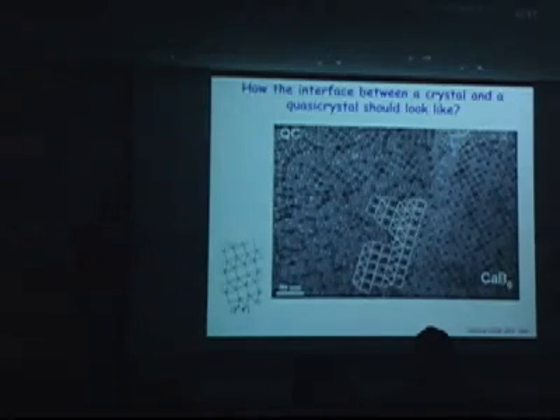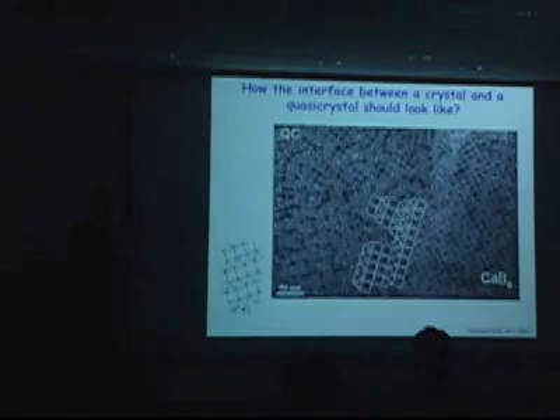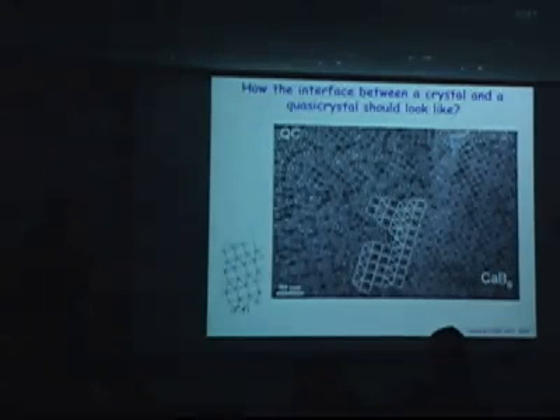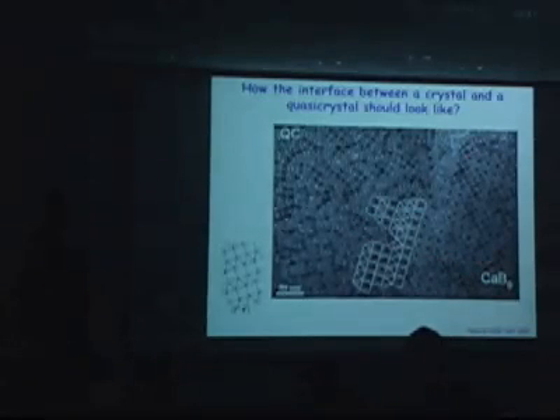For atomic systems, it was very difficult or nearly hopeless to study, because you need to map large areas with atomic resolution, and unambiguous atomic resolution. But with nanoparticles, it was a very simple experiment. We had many quasicrystalline domains, and all we had to do was look at what is at the edge of this domain, how it interfaces with the outside world. And we collected pretty large statistics of what's going on at the interfaces, and we found that indeed the dodecagonal quasicrystalline phase can pretty nicely match, for example, calcium hexaboride phase.